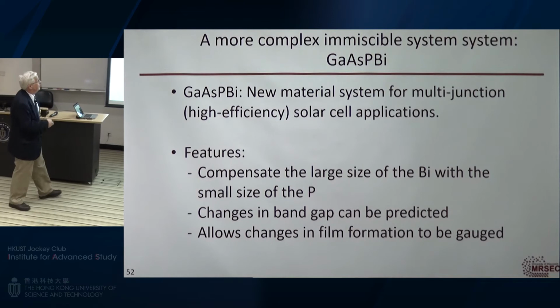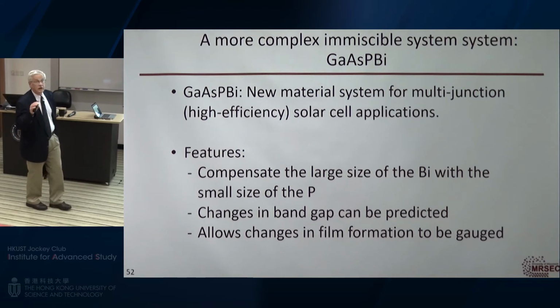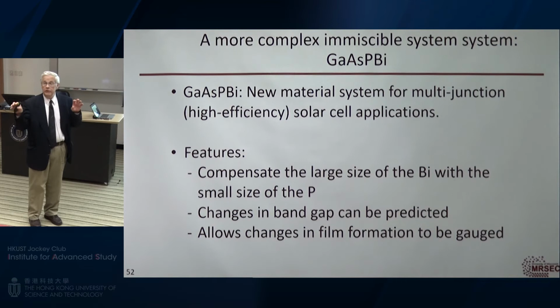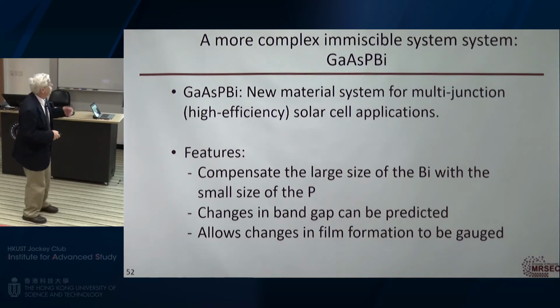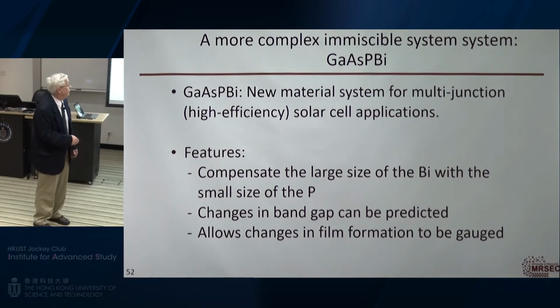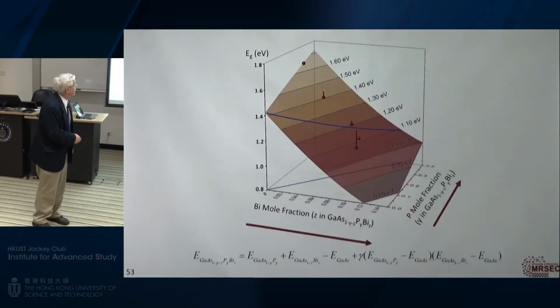So we can say, okay, if we understand the chemistry of the surface, that adsorbing certain things on the surface keeps the material from phase separating, we calculated other new materials: gallium arsenide phosphide bismuth. This material had not been grown before, or actually it hadn't been cited in the literature. But the bismuth and the phosphorus compensated. This is very small, this is very big. And so we should be able to get a lot of bismuth into the material by designing this, and then using what we know about the surface chemistry, keep it from phase separating.